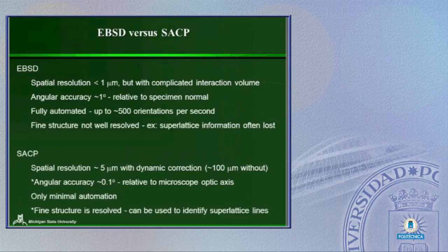First of all, there's scatter in how the Hough transform solves the orientations. But on top of that, this is a calibrated orientation. It's done based on putting a piece of silicon in the microscope and calibrating that orientation and then hoping you get your sample oriented in the exact same manner. And if the orientation angles are off a little bit in the mounting angles, that's going to cause some problems there.